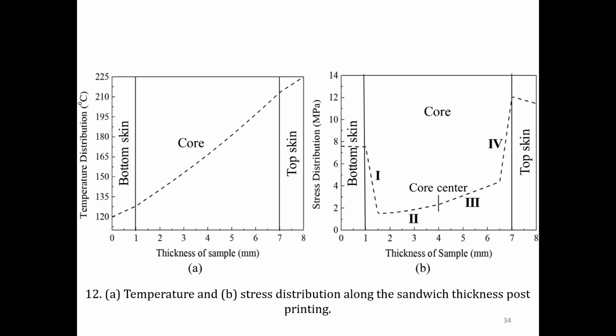And this gives us a clear idea of how the temperature distribution takes place. And if at all we can reduce this gradient, especially across points 1 and 2 and 3 and 4, what does it tell us? During this printing, if we can employ an additional cooling element or heating element as required based on the material system, on the printer bed, we can try to reduce that gradation and probably increase the load carrying capacity.